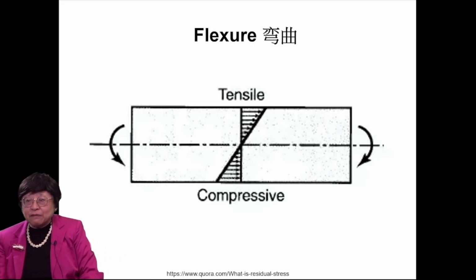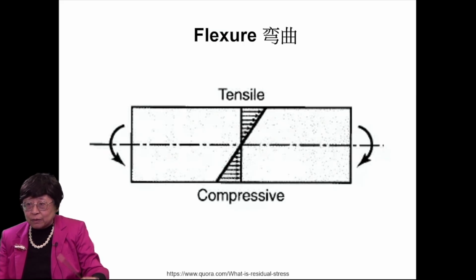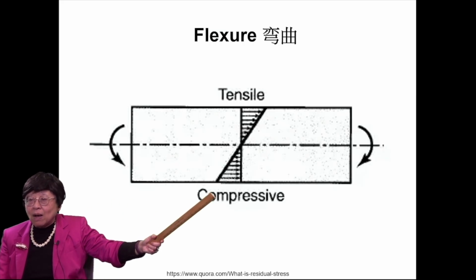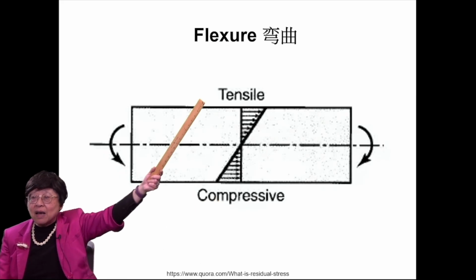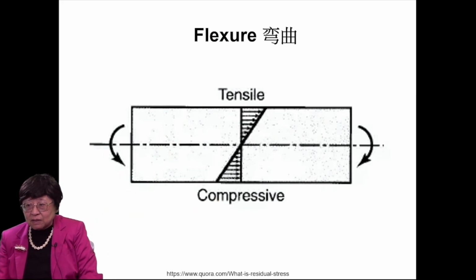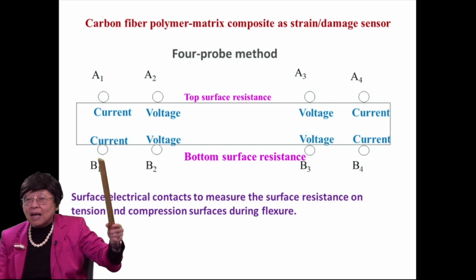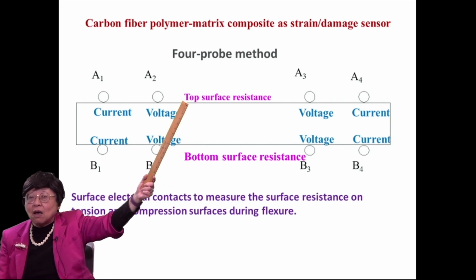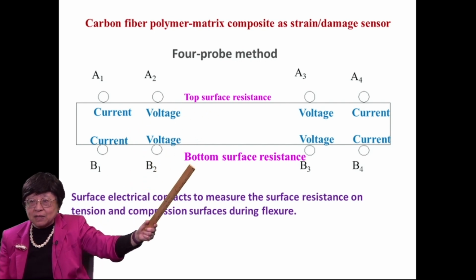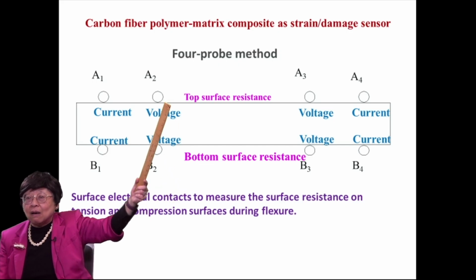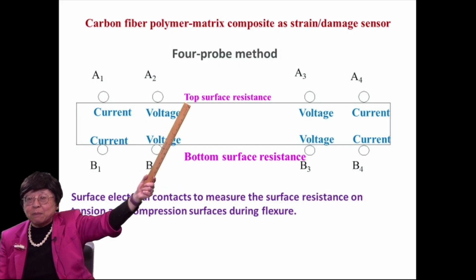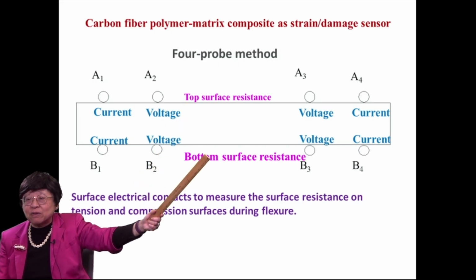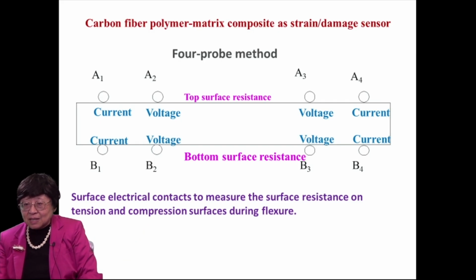Now, this is particularly valuable for sensing flexure or bending because one side is feeling horizontal compression, the other side is feeling horizontal tension. And one can apply 4 electrical contacts on each of the 2 opposite surfaces, one for measuring the top surface resistance, the other for measuring the bottom surface resistance.